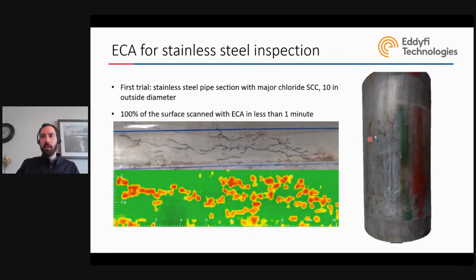So the first trial we did was on this little piece of pipe. This was, I would say, an easy trial for us because the cracks were very massive. They were very deep and very dense. So for eddy currents, you get a very nice green background with obviously the red indications corresponding to the crack. So you see here this kind of inverted C shape. You get the same thing here. So if you follow exactly all the cracks, you will find the same type of geometry. But again, this was not a big challenge for eddy currents because the cracks were so dense and so deep.